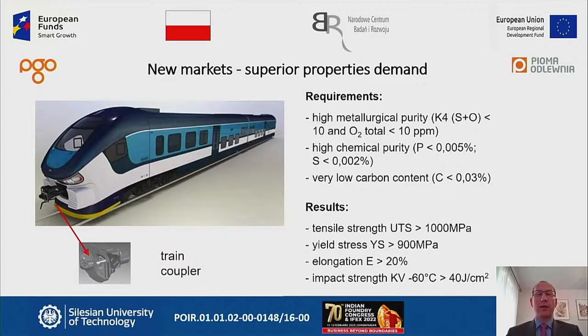And in the project, we wrote some challenging requirements, like a high metallurgical purity given by the standard K4 parameter, and total oxygen given in ppm, and high chemical purity, in this case given by the phosphorus and sulfur content. Because we were targeting in many cases low carbon steel, duplex or super duplex steels, the carbon content should have been less than 0.03%. The results we expected were tensile strength more than 1000 megapascals, yield stress more than 900, with elongation more than 20, and impact strength at minus 60 centigrade more than 40. This is this kind of extreme conditions.